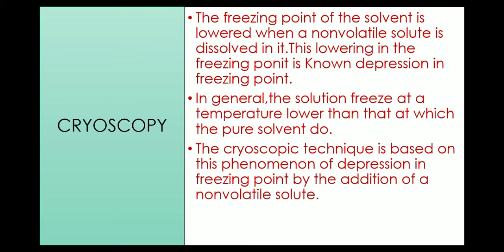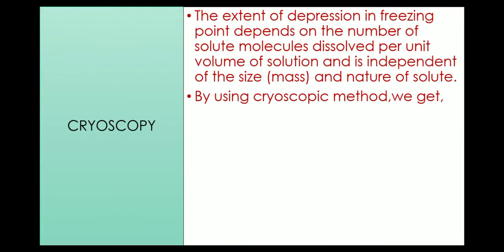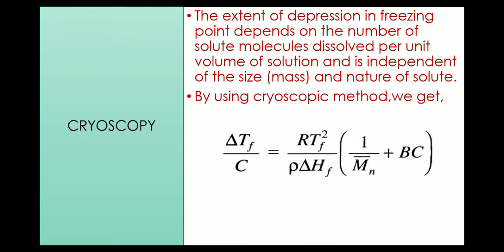The cryoscopic technique is based on the phenomenon of depression in the freezing point by the addition of a solute. The extent of depression in the freezing point depends on the number of solute molecules dissolved per unit volume of the solution, and it is independent of the size, mass, and nature of the solute. By using the cryoscopic method, we get an equation: delta Tf divided by C equals R·Tf² divided by (rho·delta Hf) times (1/Mn̄ + BC).